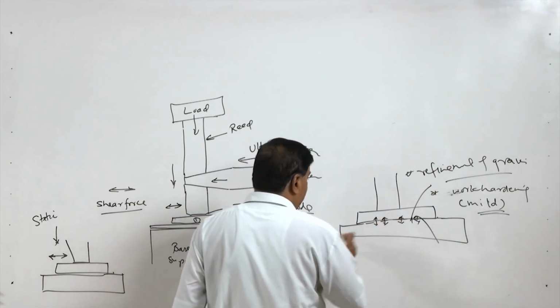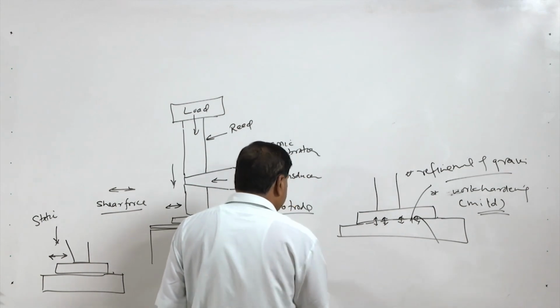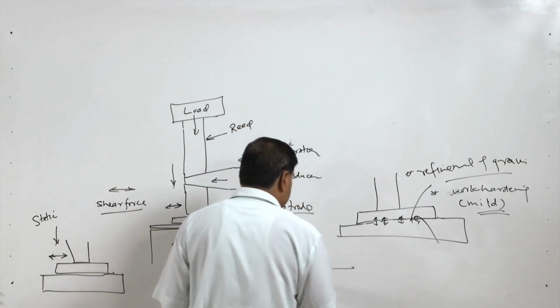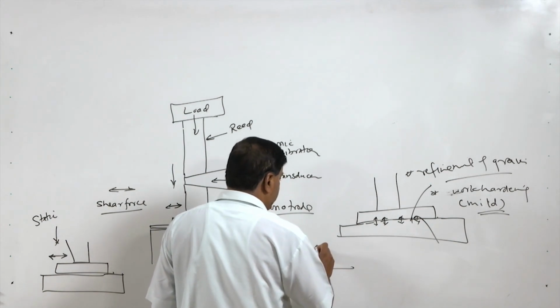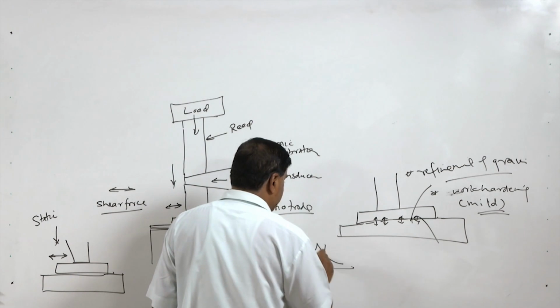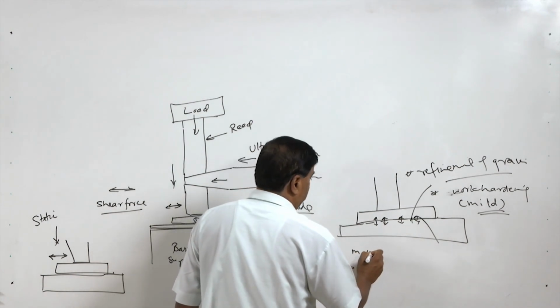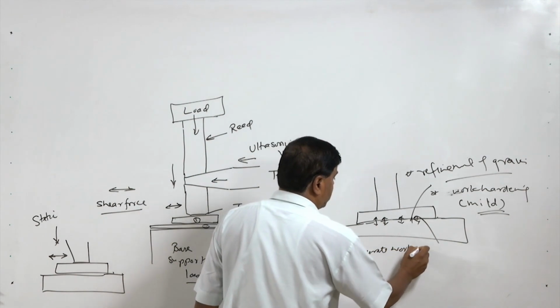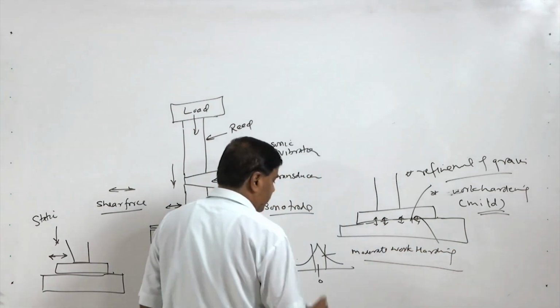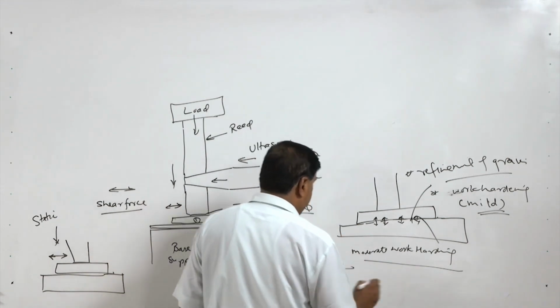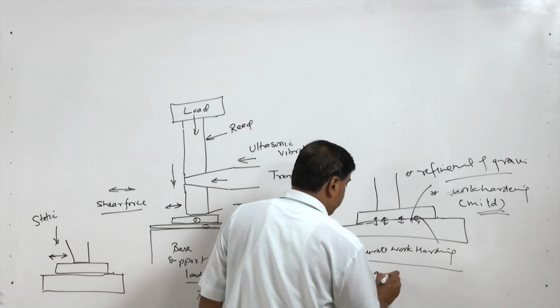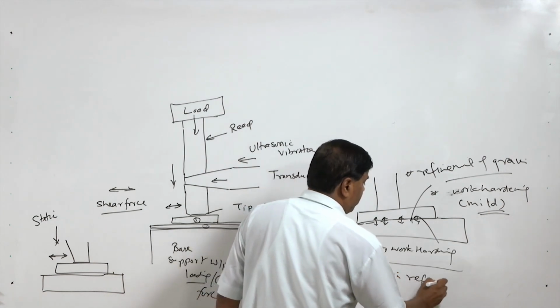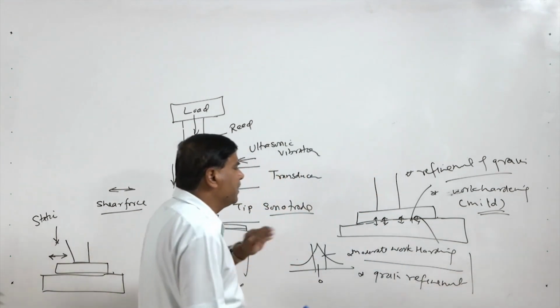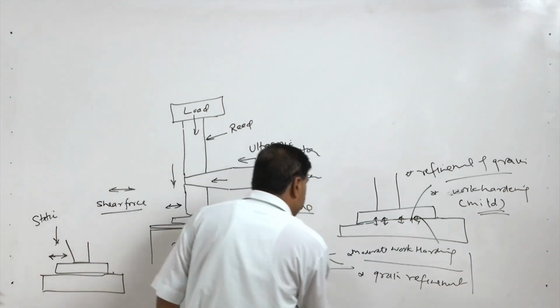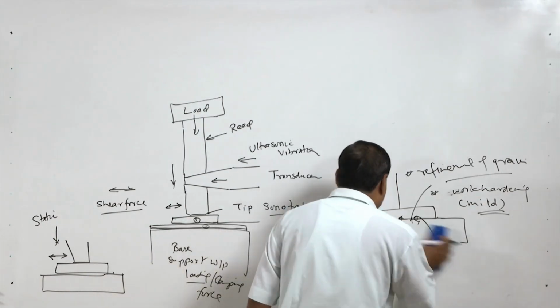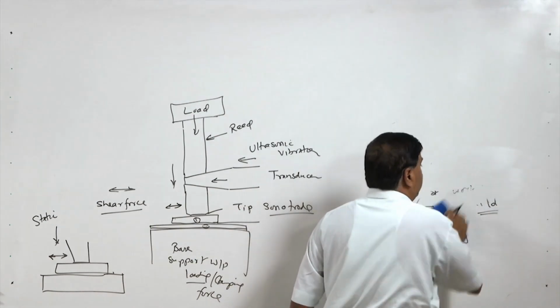So, if we measure the hardness at the interface, we may find that if this is the interface, then on approaching towards the interface we may find an increase in hardness, and this increase in hardness is attributed to the moderate work hardening which is taking place due to the elastic plastic flow of the material at the interface, and additionally the grain refinement of the material at the interface due to the continuous deformation in both directions of the material in the course of the ultrasonic welding process.